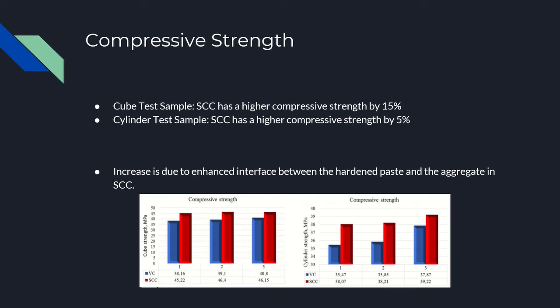When vibrated concrete, VC, is compared to an SCC sample at the same water to cement ratio, SCC is seen to have a higher compressive strength of up to 15% for the cube and up to 5% for the cylinder. This improvement in compressive strength is due to the enhanced interface between the hardened paste and the aggregate in SCC. The figure displays the information graphically.